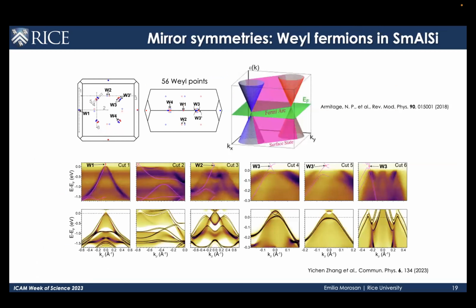Then we moved on to characterize the Weyl fermions in this compound, where here the top row shows the ARPES data with the theoretical calculation overlaid for the bulk, and then the bottom line is the surface calculation. And so there are 56 Weyl points that are predicted to exist in this compound, and then this is what you would expect the Weyl points to look like in reciprocal space.